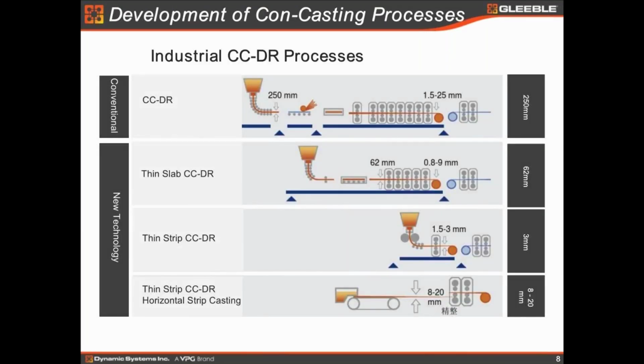Okay, now here are some examples of the CCDR process. From conventional, we know it's a slab. Normally the thickness will be around 250 millimeters, and then continuous rolling to 1.5 millimeters to 25 millimeters thick. But when the technology developed, especially when thin slab continuous casting technology developed, the length of the production flow became very short, from like half a kilometer down to even 100 meters. So this development not only makes steel casting and rolling much more efficient, the key is also that the investment is much less than the conventional ones.